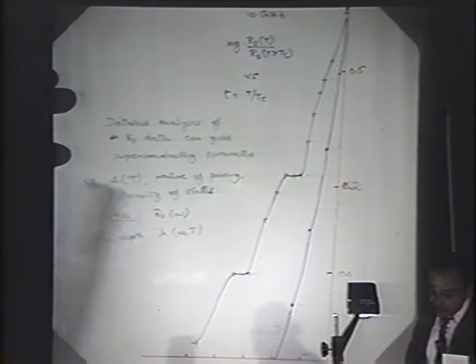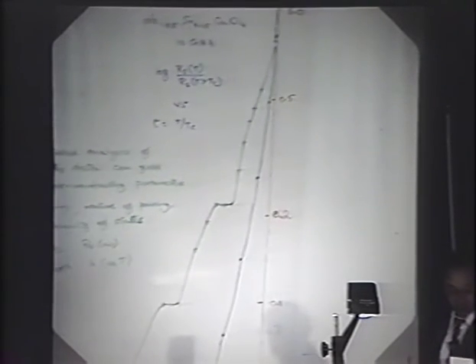From such data, one can get information about the temperature dependence of the gap, perhaps the nature of the pairing, and the density of states. One final comment is that this type of measurement is particularly attractive in these materials because other probes, like specific heat, are much harder to measure as far as their detailed temperature dependence goes because of the lattice background, whereas these are purely electronic. Thank you.